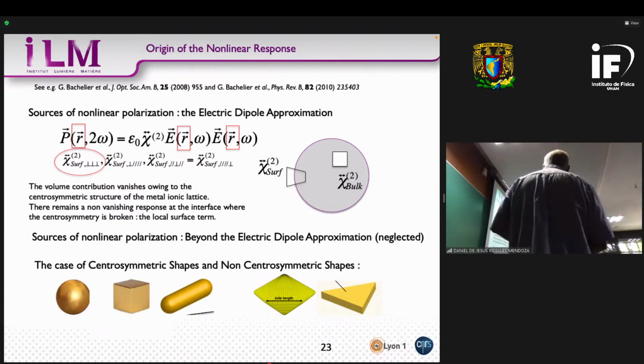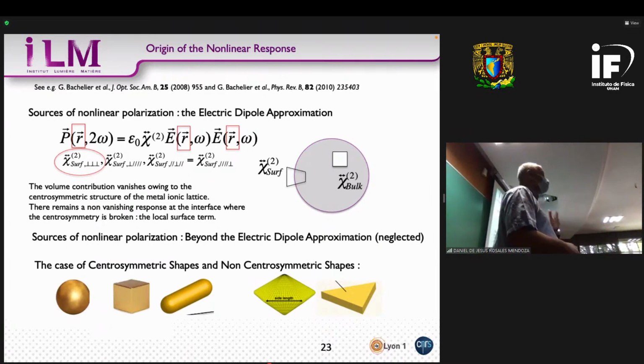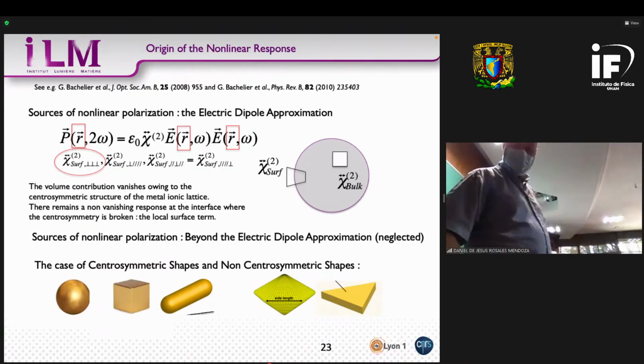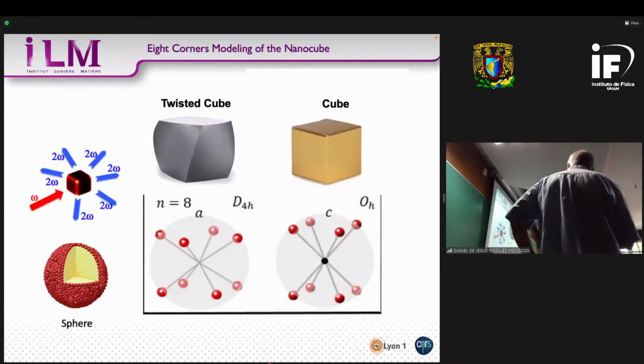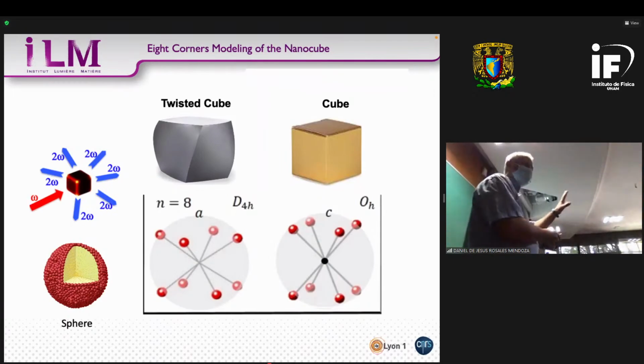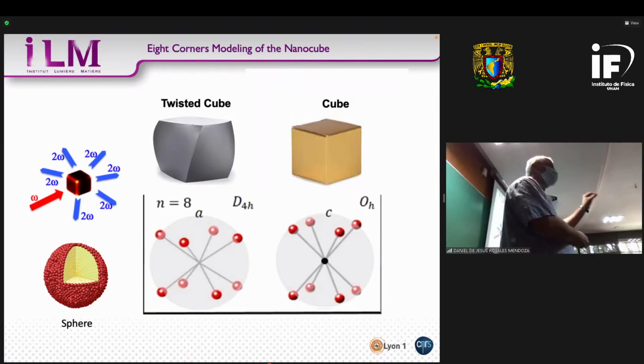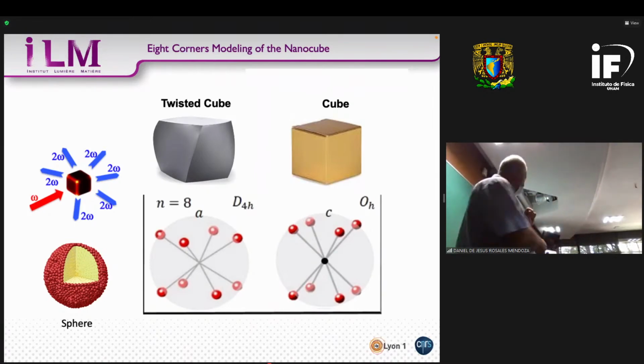So we've discussed a whole lot of different shapes, and now we can develop syntheses for many different shapes. The first thing with nanoparticles, and how this relates to liquids: if you take a cube, for example, you have 8 corners, and the 8 corners will be the seat of the second harmonic response. The faces here, you see, are dark. This is a simulation. They're dark, and that means their response is negligible compared to the corners.